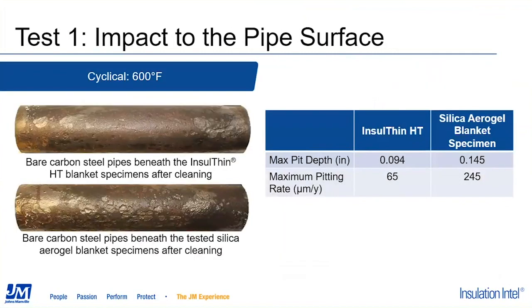If we take a look at the actual results here, this is going to be the results of the first test. And you can see on the left the pictures of the pipes. The top pipe is going to be your Insulthin HT, and the bottom pipe is going to be the silica aerogel pipe specimen. And again, we're going to go back to that pitting and crevice corrosion that we were talking about. And what we're looking at on that chart on the right is going to be the pitting depth. So you can see the maximum pitting depth on the Insulthin HT sample was less than that of the silica aerogel specimen.